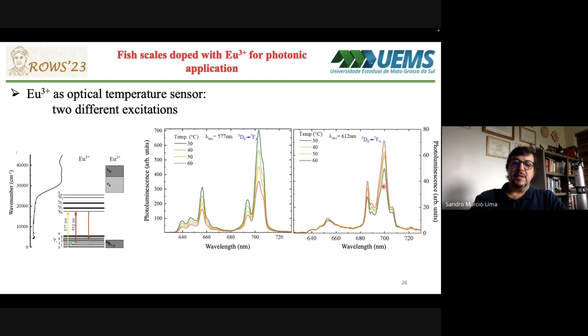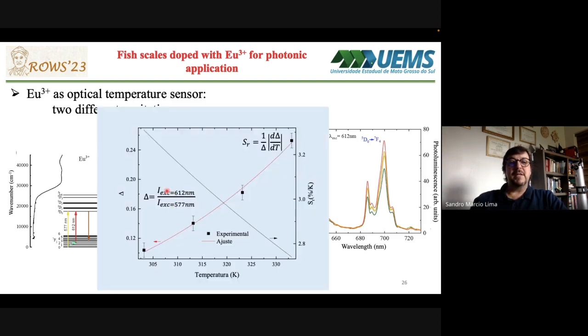By calculating the delta, that is the ratio between the emission intensity registered with excitation at this wavelength, by this wavelength, this growing curve was determined, and it was fitted by an expression that considered the Boltzmann distribution between thermally coupled levels. With this theoretical curve, because we have more points, it was possible to calculate the relative sensitivity that is defined by the temperature dependence of the fluorescence intensity ratio determined here, normalized by the signal.